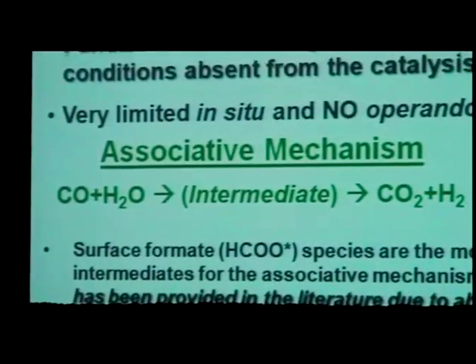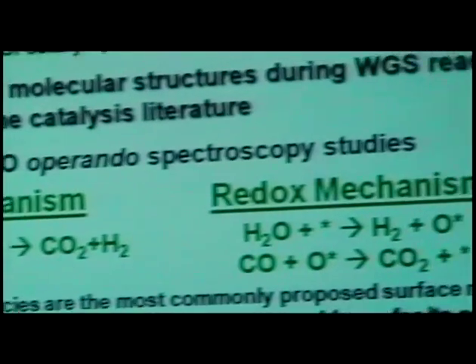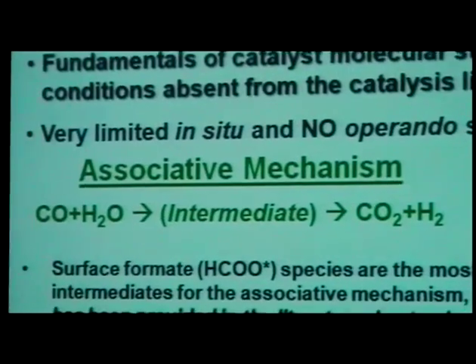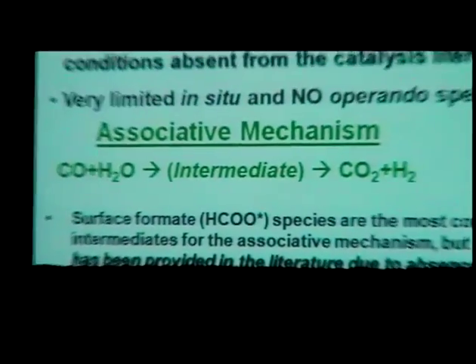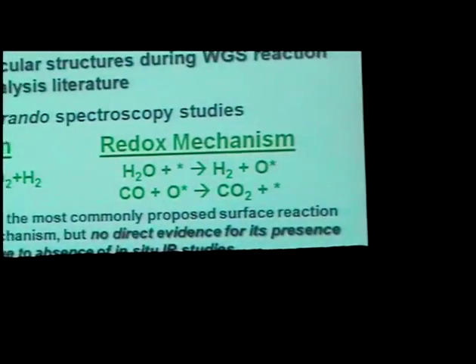However, there have been some old in situ Mossbauer studies, but all the other studies have been by pulling the catalyst out from the reactor. This material is pyrophoric. It oxidizes when you pull it out, and so it is changing, and you really should characterize it during the reaction conditions. And the conclusion from this early work is that the active site is an iron 3, iron 2 redox couple.